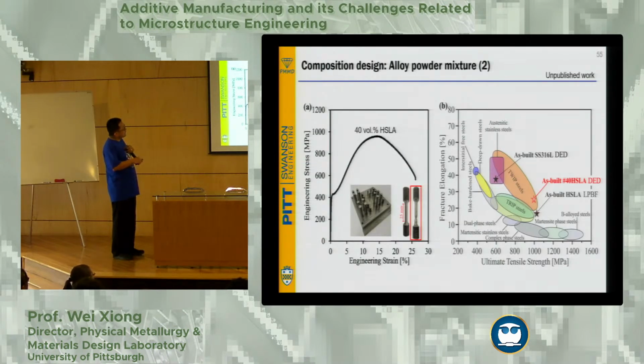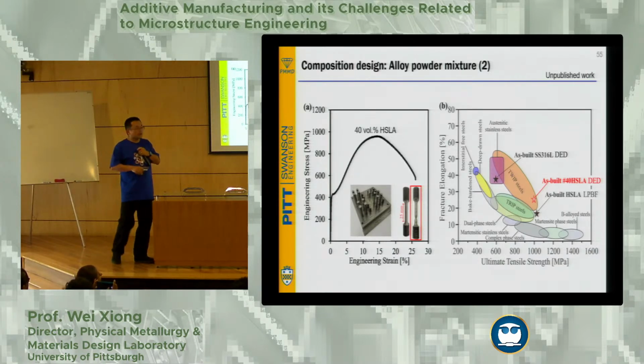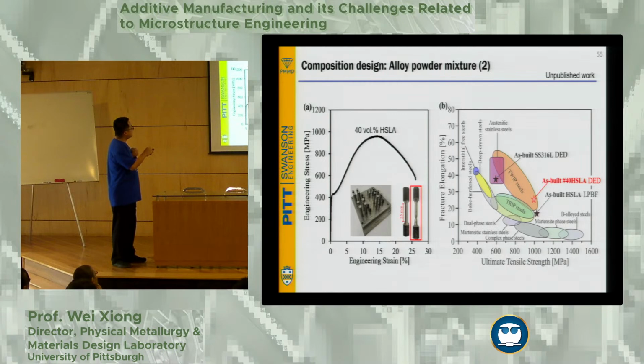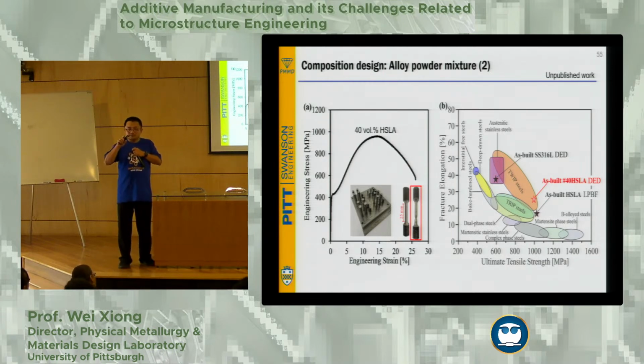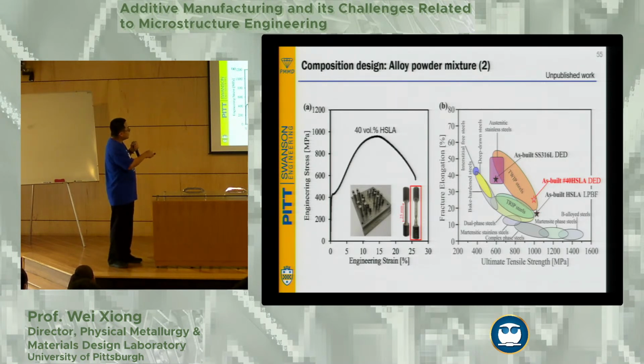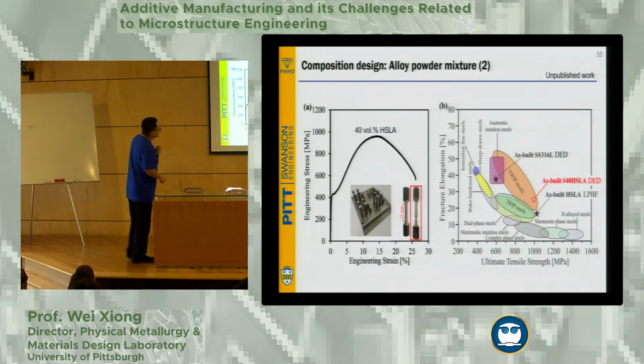I have to say I missed one slide here. Another encouraging thing about this new alloy is that we don't have very high elongation, but we have very high UTS. That means you can better use this in car structure materials, because once you have a strong impact, you don't want the ductility too high. In a car crash, you don't want it to deform too easily, so you want lower ductility, or just enough ductility, but then you can quickly reach the UTS. That's actually the high performance of these TRIP and TWIP effects.